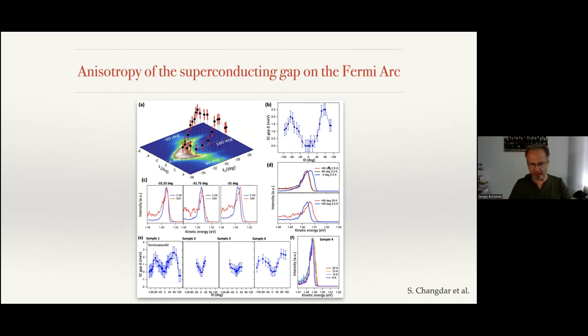So if you compare plus 90 degrees, minus 90 degrees, and 0 degrees, so you can code the position on the arcs by these degrees. So you compare this point with these two, and you clearly see the effect. And then you see how the gap closes, and then you see how this is just supporting data for the paper. And this is reproducible, so you can measure the gap near the node in different samples. You can see that superconductivity is reproducible. So now we know that there is a node of the superconducting gap at the Fermi arc.